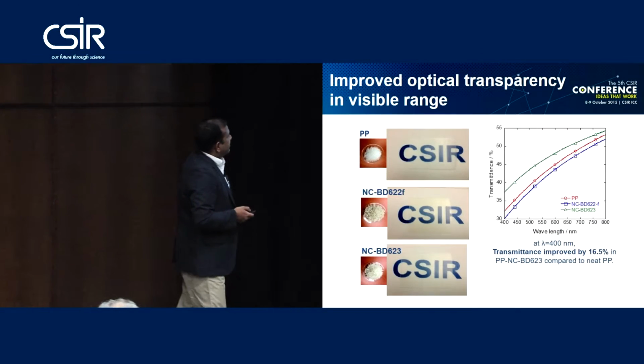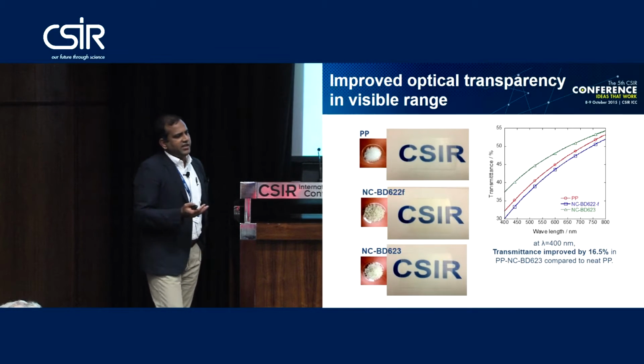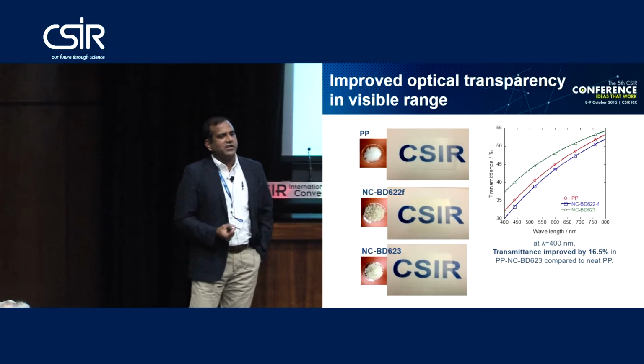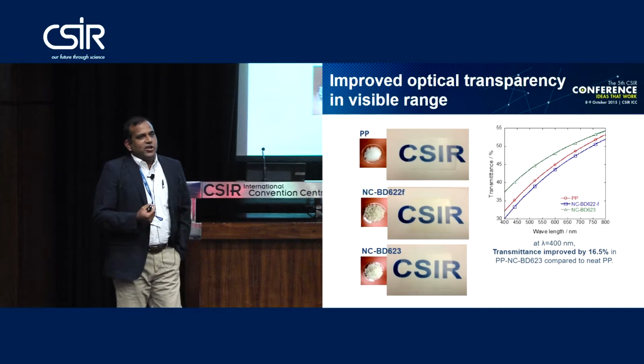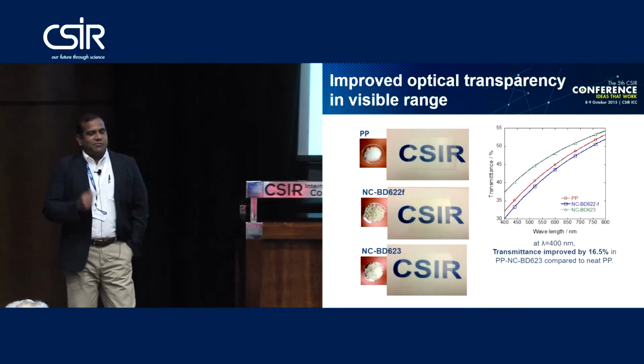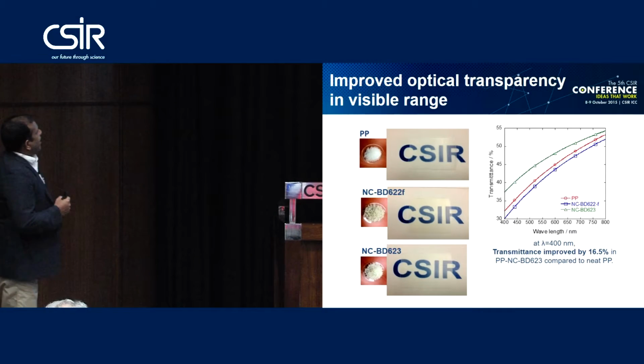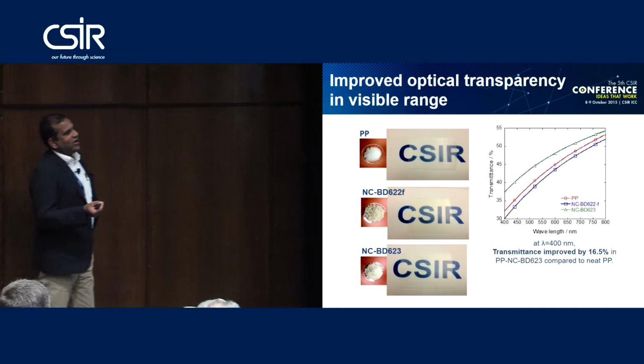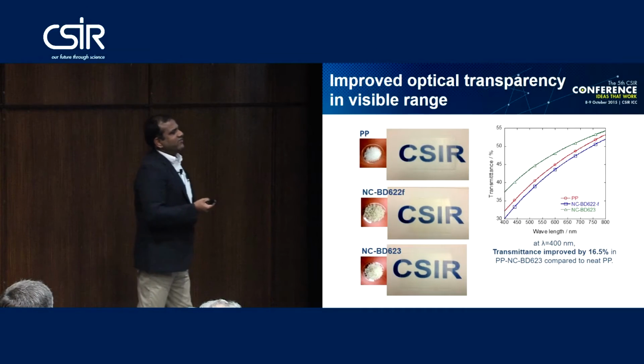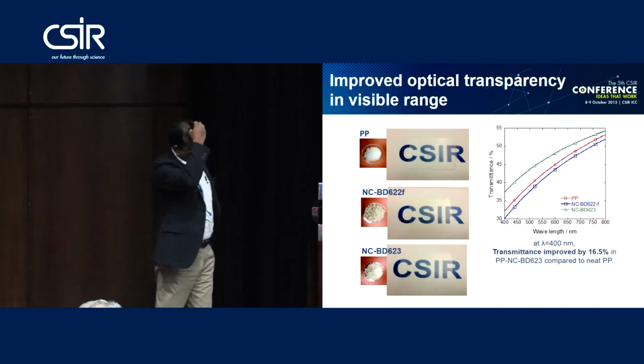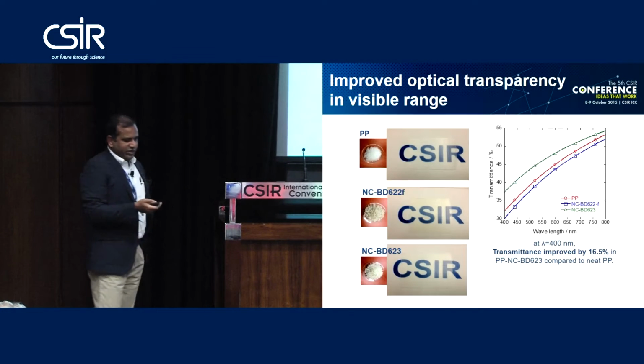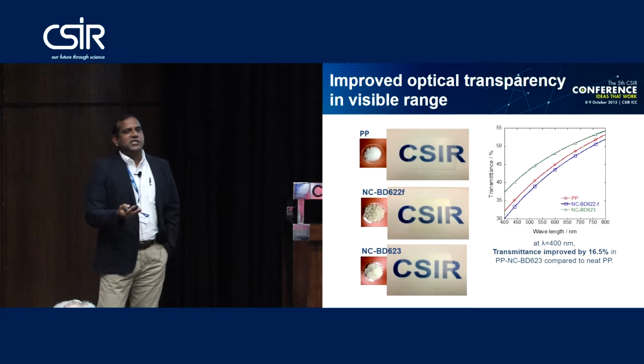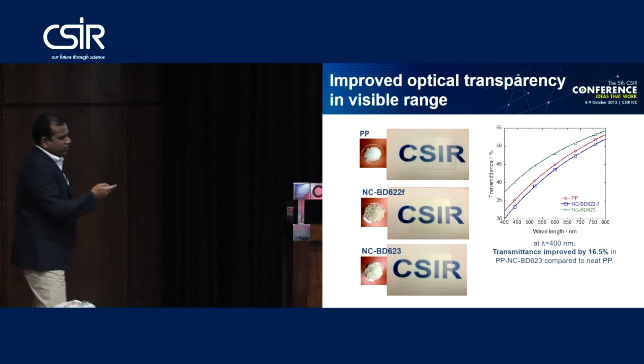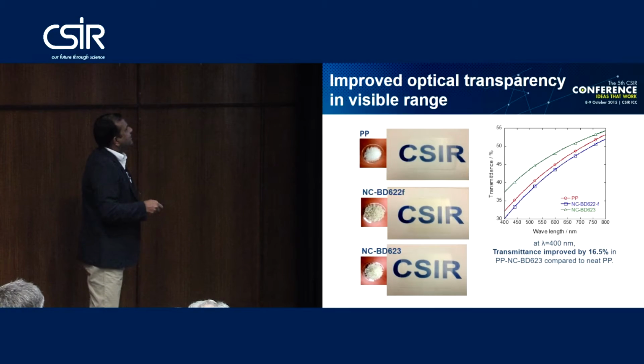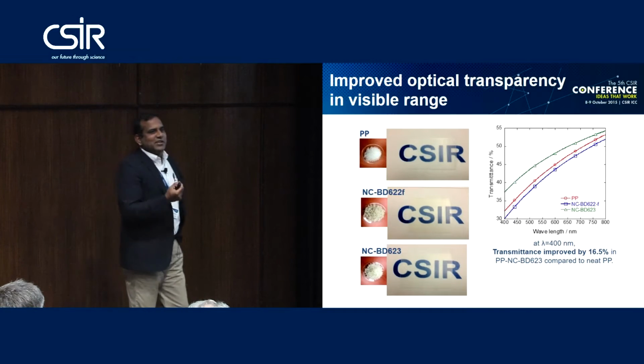One of the things the packaging industry needs, its main criterion, is transparency. So packaging material must be transparent. But if you add a filler inside the polymer matrix, for this reason you can see very little use of composite material for transparent packaging, because if you add the filler, you will immediately lose the transparency of the polymer matrix. But what we found in our research is that if we add nanoclay particles inside the polymer matrix, you can even improve the transparency.